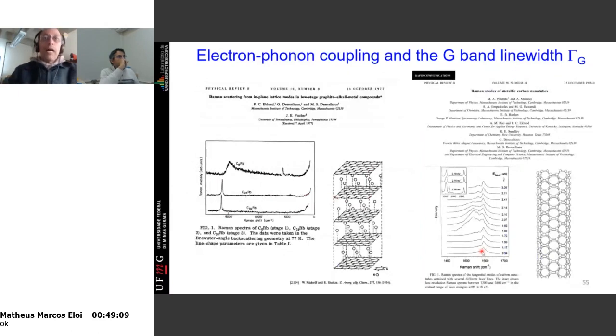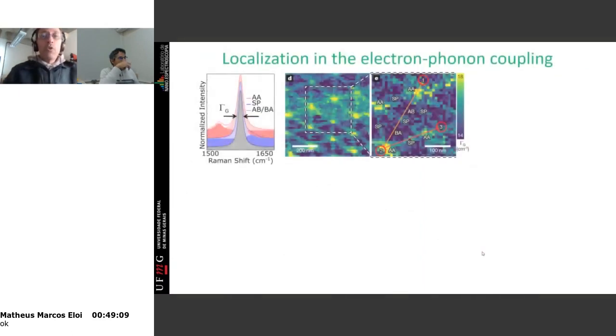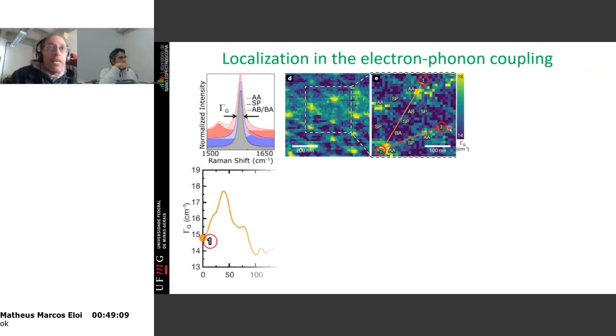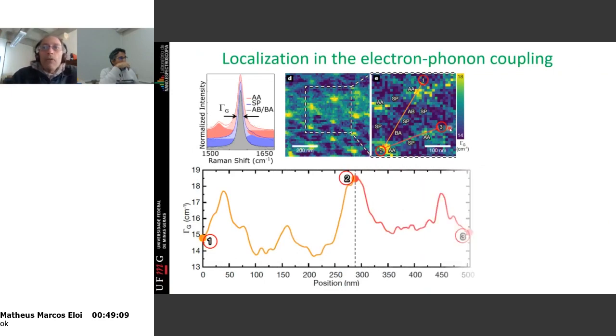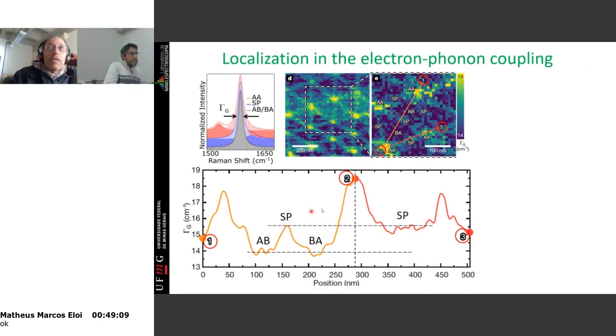All right, I will jump further ahead to go to the nano optics and ask, what happens if you look into the line width of this peak by moving along the structure of the moiré pattern in the twisted bilayer graphene? You see the line width going up and down, and the lowest level is when you cross the AB and BA stacking situation. And when you cross the strain soliton, or when you walk along the strain soliton, you have the same level. And when you reach these AA points, you have the highest value.